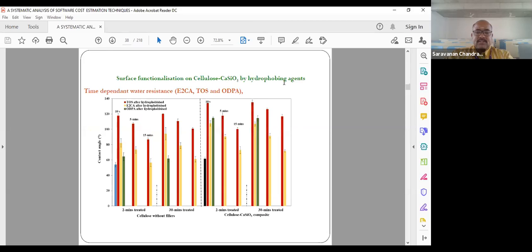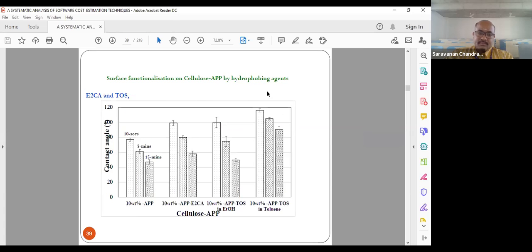Next slide. Okay, so this is the one with the cellulose with the calcium silicate. As you can see, the contact angle is almost 140 degrees. The water contact angle, the red line, which is the TOS, is a silica, which is the most effective hydrophobic agent. E2CA, ethyl-2-cyanoacrylate, is also an efficient hydrophobic agent for changing the surface from hydrophilic to hydrophobic. But the ODPA is not suitable, because ODPA does not interact much with the calcium or the other metals which are available in the cellulose film.